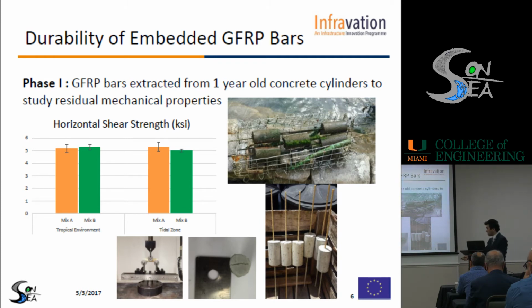You can see the test setup over here. It's like a three-point bending test. You put your rebar, and then you apply your load at the mid-span, and then you get to see this kind of failure. Basically, it's going to be the horizontal shear between your glass fibers. So that's what we did.